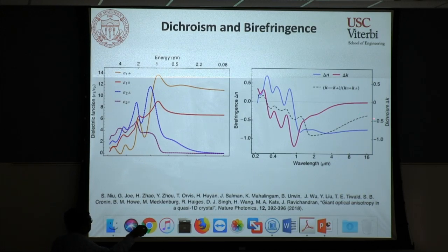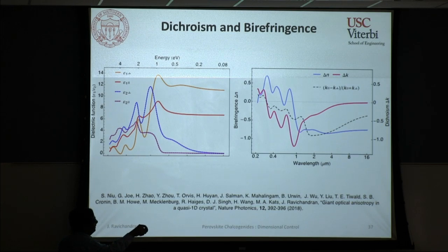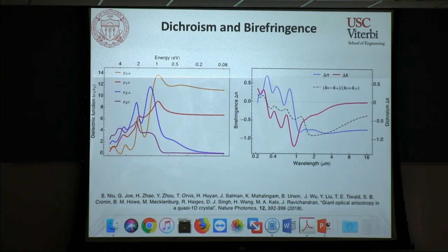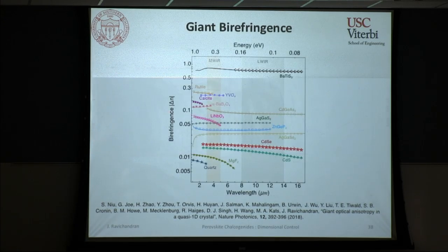And what we found was that the dichroism showed a very broadband large value, and also it turns over at some point. But the birefringence, which is this real part of the index, is very, very large compared to most materials that we have seen. So how high was it compared to most materials?